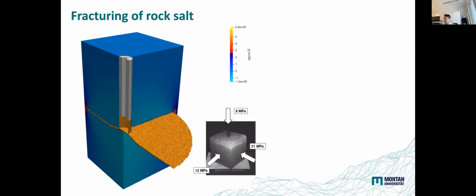And in the second case, the vertical loading was the minimum. So we saw this horizontal fracture development, and the initiation of the fracture was picked up. We did not specify a small horizontal fracture or a vertical fracture as in the earlier case. So it was initiated just at the bottom of this open hole section, and this result was based on the quasi-static or the successive energy minimization.